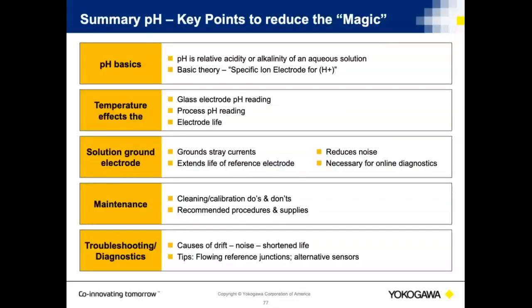We've taken about 45-50 minutes here to go through some of the basics of pH. We know that pH is the negative log of the hydrogen ion. We know that the more hydrogen ions we have present, the more acidic a solution we have. The less we have, the more hydroxyl ions we have. Basically, those hydroxyl ions will cause a higher pH. Basic theory: output of the electrode is 59 millivolts per pH unit at 25 degrees C, leading to the next topic, temperature effects. What affects the measurement? The output of the glass electrode is affected by the temperature. The process pH reading does affect the measurement.